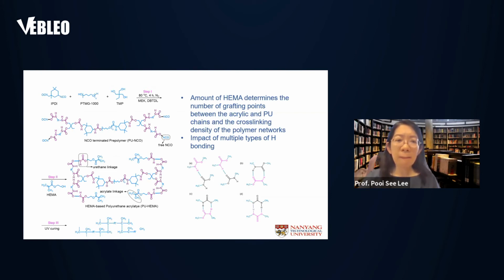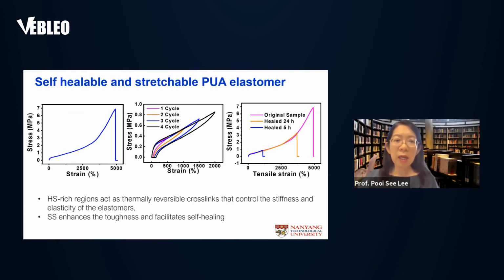So this HEMA-grafted PUA has a very high stretchability, as shown in the stress-strain curve and multiple cycles with very low hysteresis. And more interestingly, due to the hydrogen bonding, it has good self-healability, as shown in the figure on the right, where upon healing, the mechanical property can also recover to a certain extent.